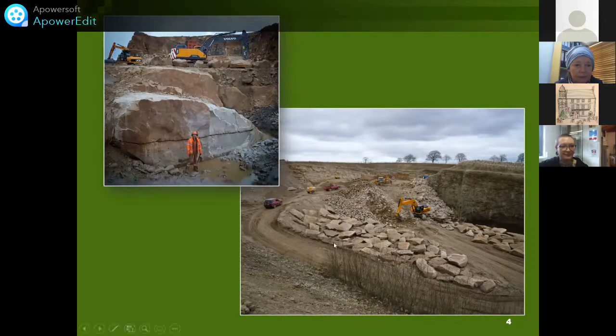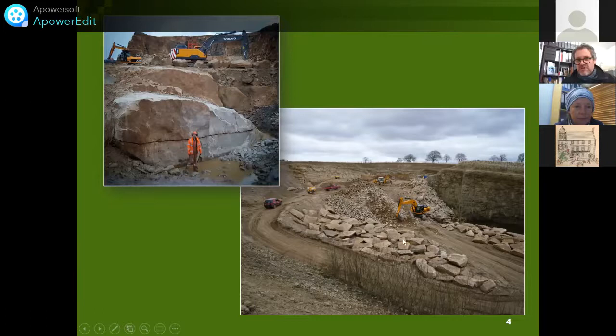And then here down below, this is Swinton Quarry. So you can see that the geology is different here. The block is much lower, much smaller. And here we've got some rubble that we're producing. So we're producing rubble from higher up in the strata here, and then lower down in other areas of the quarry. As we go lower down, we can produce this block.